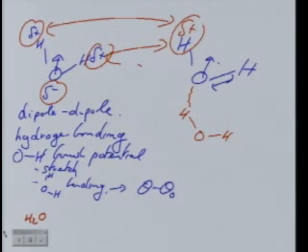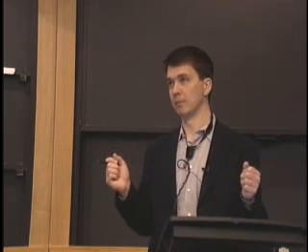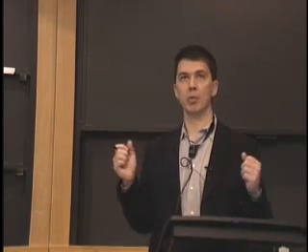I would always say, before you get into complicated models, take the simplest form and see where you get. For bending, you could literally take a quadratic in the bond angle. That allows you to do reasonable stretch around the equilibrium geometry. And a water molecule does not flop over. Its hydrogens don't really flop over that easily. For stretch, you could again just use a spring constant, so R minus R naught squared. And if you feel you go too far away from the equilibrium bond length, you could have more complicated potentials. But an OH bond is quite stiff. So it's not going to vibrate with an enormous amplitude.